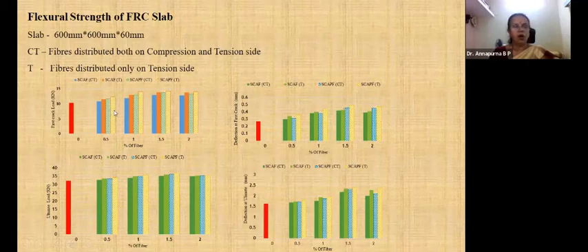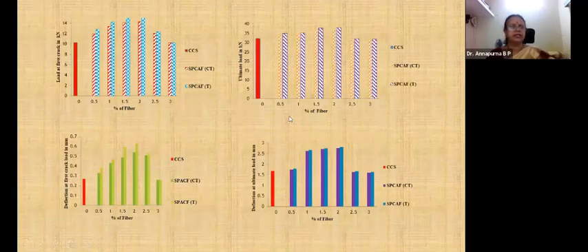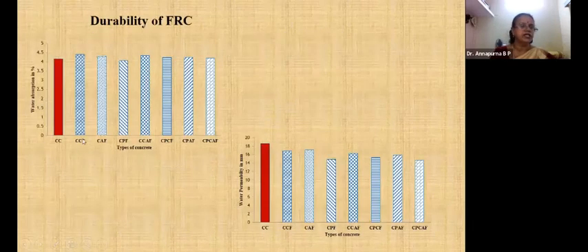Along with the plastic fiber, it is showing an increase in the flexural strength, and the deflection is also of the same pattern. So this is durability. When we check water absorption, for natural fibers the water absorption is more compared to the conventional concrete, and plastic fiber shows less water absorption. The other fibers show similar behavior.